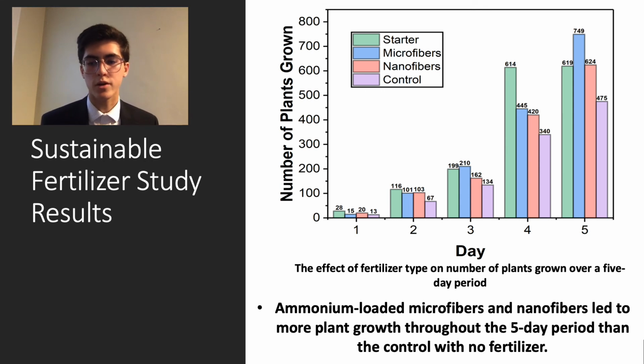Plant growth from the commercial fertilizer leveled off in the last 2 days, while the ammonium-loaded microfibers and nanofibers continued promoting growth, suggesting something interesting, that maybe this commercial fertilizer has a built-in slow release mechanism that allows it to steadily release over the last 2-day period, whereas a potential further direction of study for my materials would be how to incorporate that process of slow release, just as is seen in the commercial fertilizer.